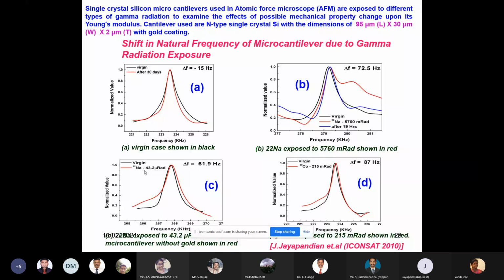That is very important. While using a sensor for measurement, it has to come back to the virgin position. But here we observed that some additional mechanism is required to bring it back to the original for the next measurement. Our students are working on that at each stage as they come across it. In the same way, this is the virgin cantilever with sodium-22 for different exposure times.